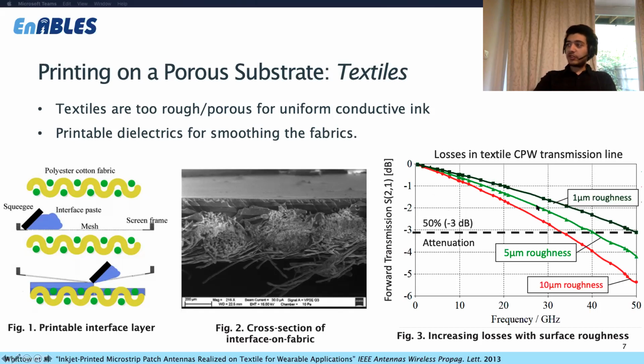And in figure 3, I just have an example of the high frequency losses to make a point that surface roughness is indeed a problem. So if you have a 10 micrometer surface roughness, your 50% attenuation in a standard transmission line can go down by more than 10 gigahertz compared to 1 micrometer roughness. So it's in the interest of everyone to print and work with smooth surfaces. And even with textiles, there are methods to make them more printing friendly.